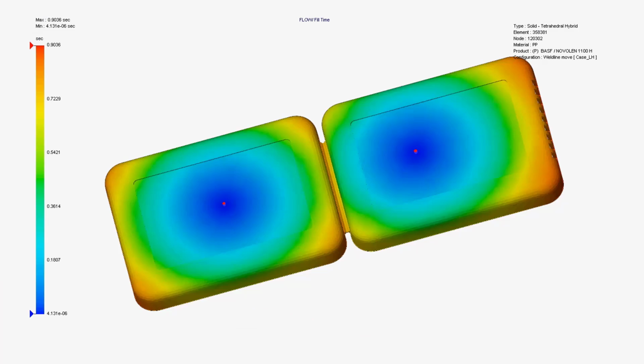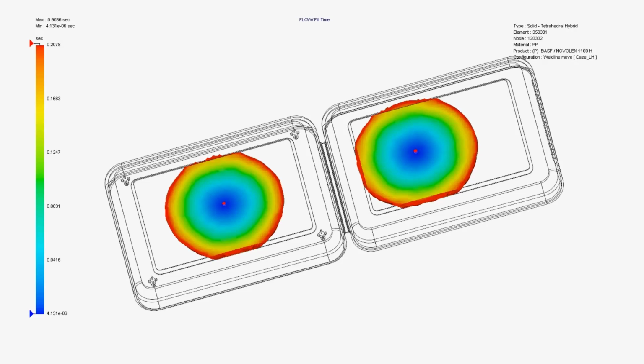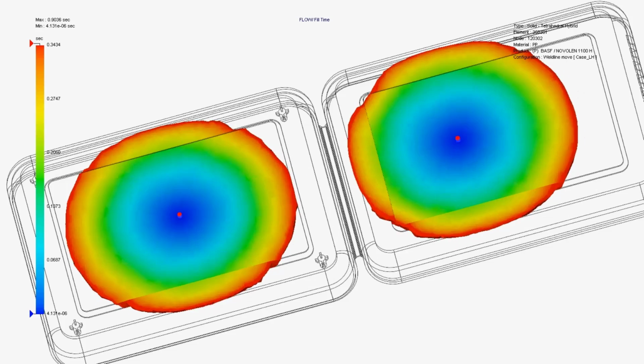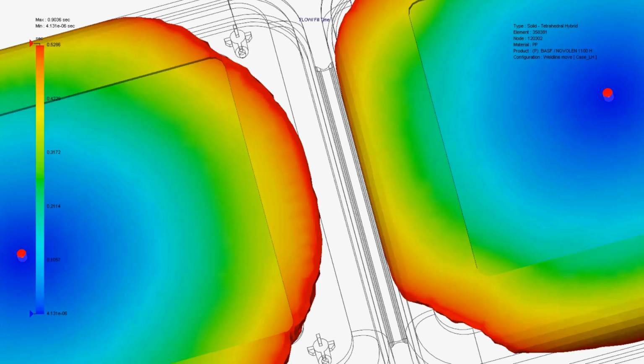or oriented, our weld line shows up right in the middle. By changing the placement of the injection locations in the simulation, I'm able to move the flow of the material so it flows across the hinge from one side prior to hitting the other side. So my weld line's not in the middle of the hinge anymore. I get a more robust hinge, and it makes my weld line an area that's less visible on my part. So I'm going to have a better part design, a less visible weld line, and a more robust hinge in this case.